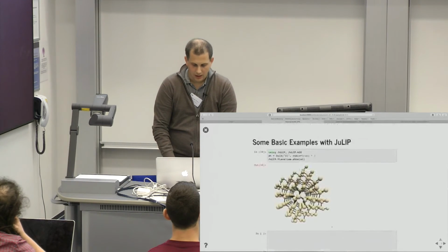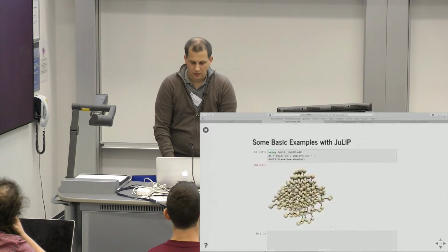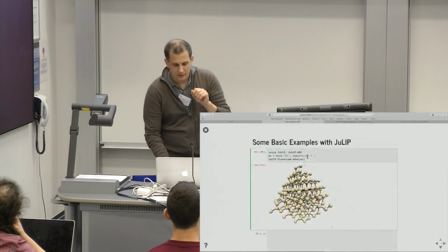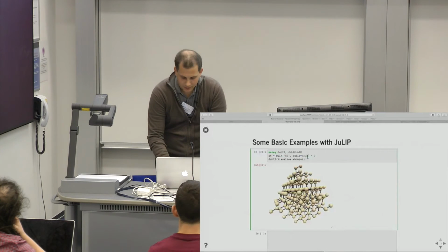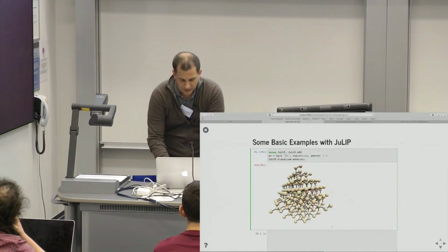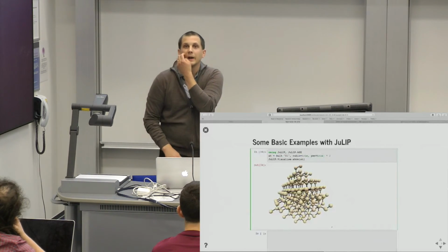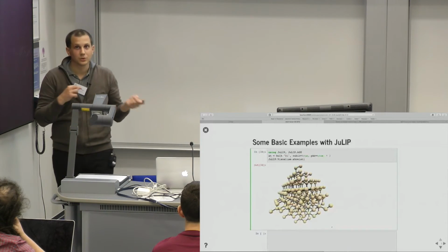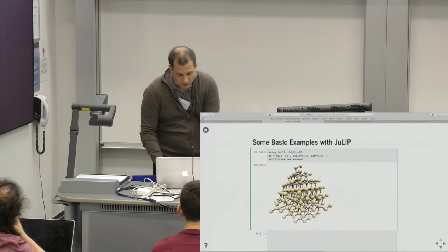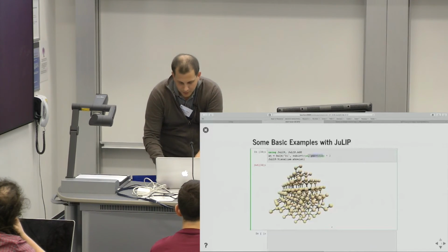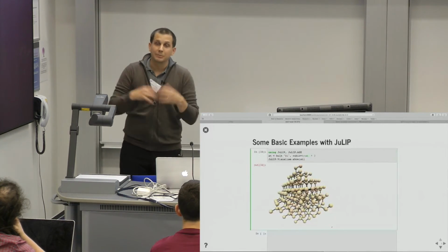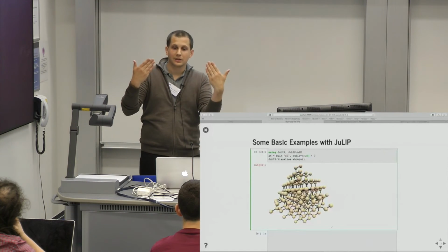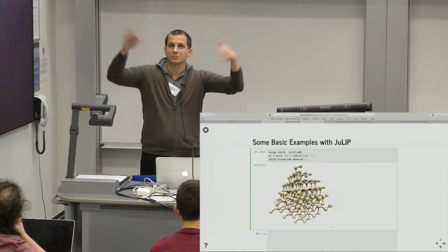Good question. You know the crack propagation animation? Let me start with that one, then I'll go to the crack. I'll make something explicit that I didn't write out: PBC, periodic boundary conditions. You can do that, but you cannot do that for a crack. Another thing you can do is clamped boundary conditions. I put something on the outside that somehow mimics what the outside crystal is.